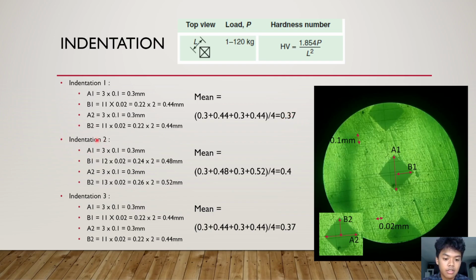And for the second indentation, we get 0.4, and I find this weird because we did not change anything. Maybe there was a mistake in our measurement, but we'll stick with 0.4 millimeters. And for our indentation number 3, we also got the same as indentation number 1. We got 0.37 millimeters for its mean diagonal.